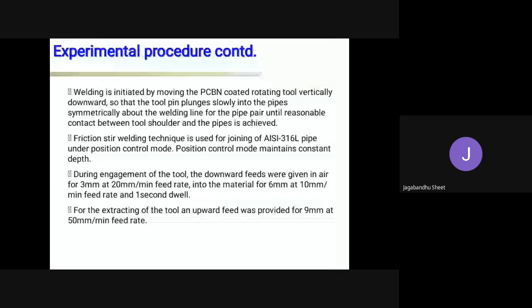So the welding has been done with a PCBN coated tool, which I have already mentioned. The experiment is conducted in position control mode at constant depth. So the depth was kept constant at 6 millimeter.